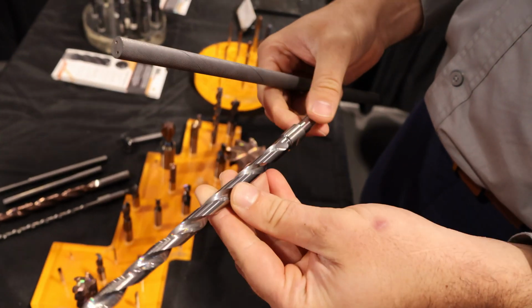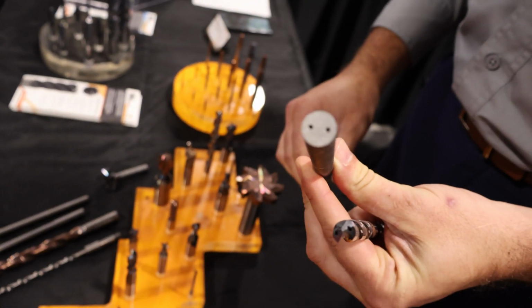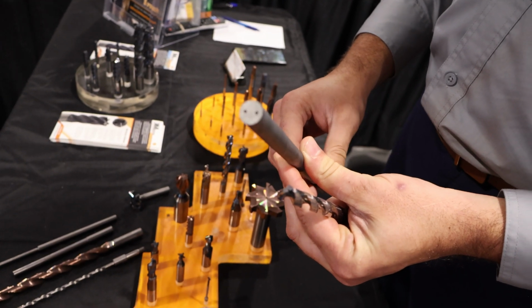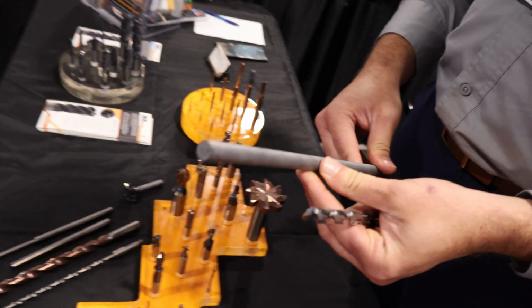Yeah, so this is an aerospace drill for aluminum. And we'll accept a through-spindle coolant rod like this. Wow, so that's how the rod comes. It's got this weird turned finish on the outside. Yeah, that's a die. So in the green state, it's pushed through this die, and there's wires in the coolant holes, and that's what dictates the pitch inside the rod of the coolant holes. Okay. And then it's sintered. Sintered, like melted together kind of thing. It's basically baked at a high temperature. Yep. And that's what turns it into hard carbide.